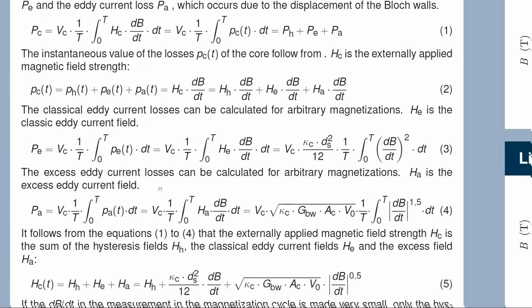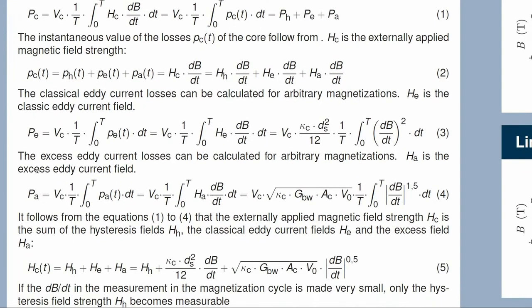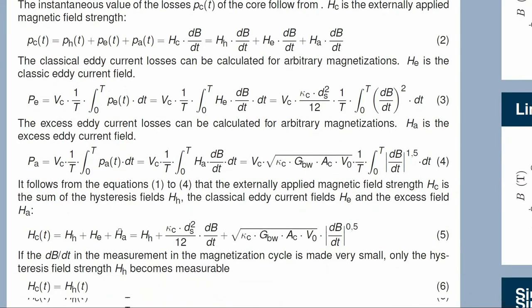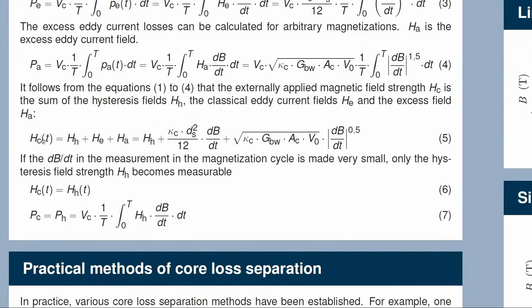In the literature you find equations 3 and 4 for the eddy current losses, and they are also a function of the instantaneous core losses and the change of flux density. Inserting equations 3 and 4 into equation 2, you will see that the applied field is the sum of the static hysteresis field, the eddy current field, and the excess eddy current field. This dynamic part is a function of the speed of magnetization. So when you bring dB/dt to zero, it is possible to directly measure the hysteresis field, because it is equal to the applied field.